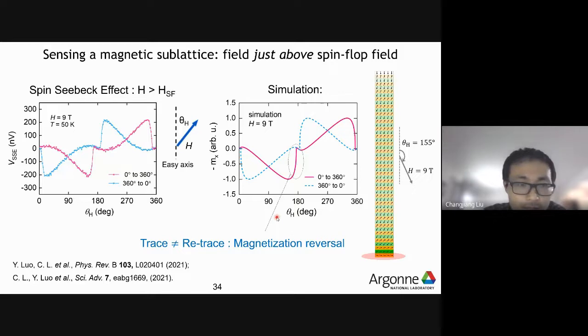Now, I just showed you the measurement at up to 6 Tesla. As we increase the magnetic field, we see that the response shows a dramatically different behavior than at lower field. You see now the curve shows a sharp jump near 180 degrees. And once you rotate the magnetic field back from 360 to 0, the curve is no longer reversible, but shows a hysteretic behavior, right? This can remind you of some hysteretic behavior in magnetic systems, just like when you have a magnetization subject to an external field,